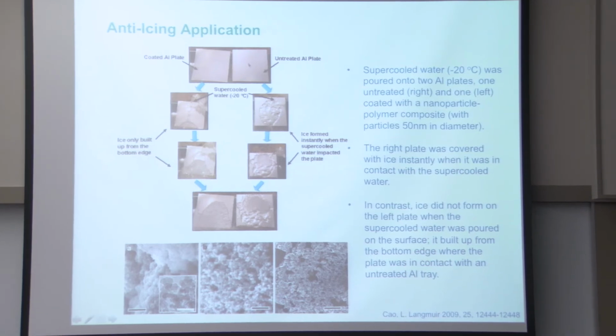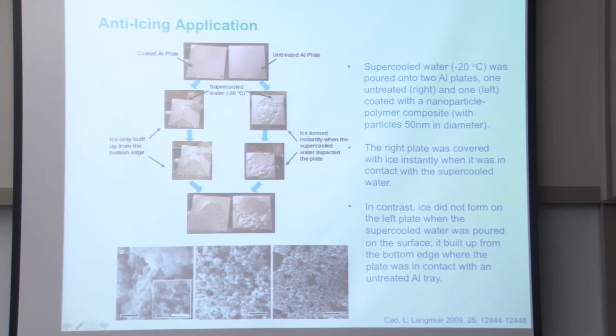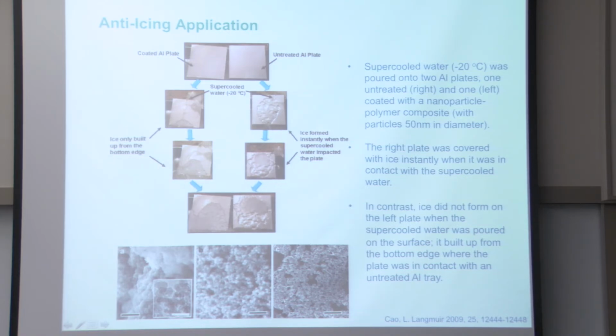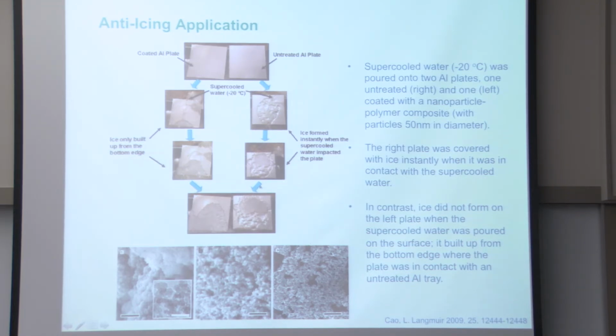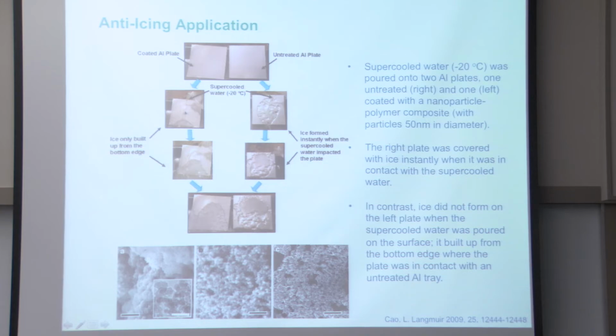Here you can see two aluminum plates—one coated, the other not coated. When supercooled water is poured and contacts the uncoated aluminum plate, ice forms immediately upon impact. However, with a coated or superhydrophobic surface, you don't see ice formation, which only occurs near the edge.